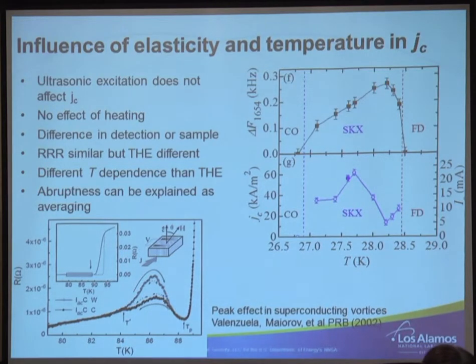So the first thing we thought is, well, maybe it's this ultrasonic excitation that we're doing that is changing the critical current, increasing it, similar to what we saw on Monday with magnetic field. Now, this same type of phenomenon happens also in vortices. Actually, this is part of my PhD thesis, where you can put AC current or AC field, and you can change the critical current as a peak effect in superconductors. So we did this with 2 types of amplitudes. And here, making twice the amplitude, we basically get the same value.